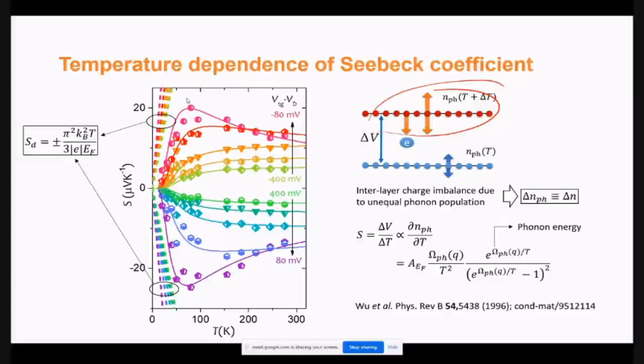Absolutely, Saurabh, you are absolutely spot on here. Because of the hybridization of phonons, you are essentially leaking the heat out, and there is a thermal conductivity between the upper layer and lower layer. We originally started thinking that we can actually have a complete thermal insulation between the two, but because of the hybridization of the two phonons, you are no longer able to maintain the temperature difference. Let me put it this way. If you want to have a heat engine, then you want to maintain a temperature difference, and this will be a high efficiency heat engine, with high ZT factors as you call it. But because of these phonons, which couple the upper layer and lower layer, you can no longer keep that temperature difference.